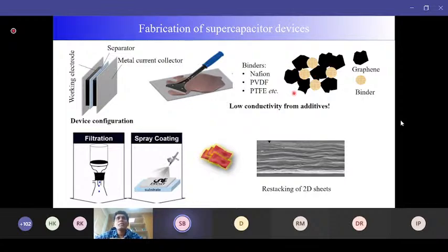And there are other methods where you can completely remove the additives, because it is necessary. If you can remove the additives, then conductivity definitely will be better. So for that, there are some other alternatives like filtration and the spray coating technique. In the filtration and the spray coating technique, you start with some dispersion of these nanosheets, and you either spray coat over the substrate or do filtration to get the film.